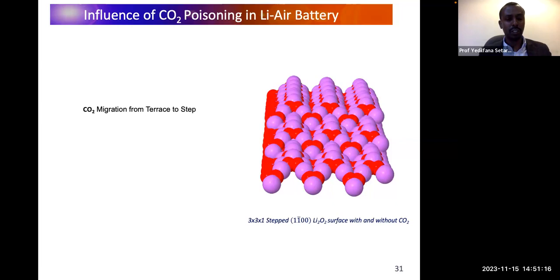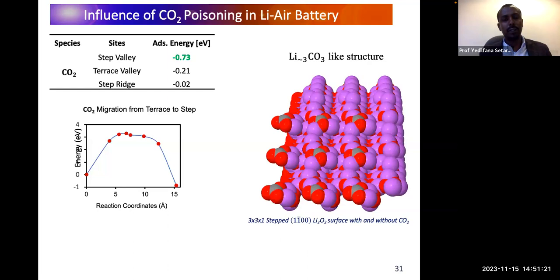We tested different sites of the 11 bar 00 lithium oxide surfaces, and we found the Step Valley site is the preferred adsorption site for carbon dioxide. As you can see here in this structure, there is some restructuring upon addition of carbon dioxide because of the formation of lithium carbonate-like structure on the surface. This definitely alters the low overvoltage pathways, the minimum energy nucleation pathways or nucleation sites.